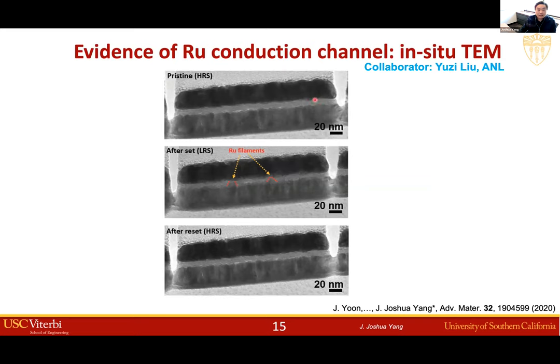So you can see for a single device that can be switched on and off in the TEM. In the pristine state, the oxide layer is clean. And after the device is switched to the low resistance state in situ, you can see the ruthenium filament actually grow and reach the top electrode. And for the same device that was switched back to its off state, you can see the ruthenium filaments are gone. So basically, ruthenium serves as a mobile species instead of oxygen vacancies in this new device. And this led to the fantastic switching behavior.